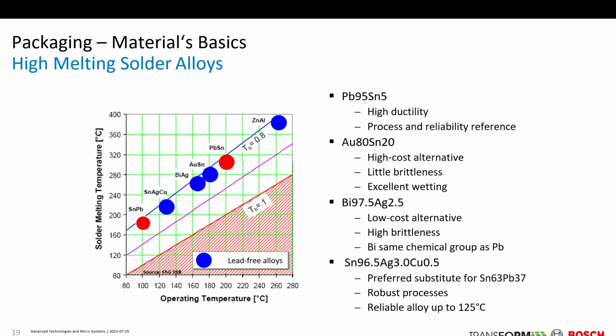Looking at alternatives for lead-containing solder alloys, because everybody wants to get rid of them. For second level packaging, we now have this lead-free solution here. It's the preferred substitute for the eutectic tin-lead. It's a robust process and quite conventional nowadays. Twenty years ago, there was a lot of technology struggle and research on how to implement this alloy for industrialization. It's very special for second level packaging.